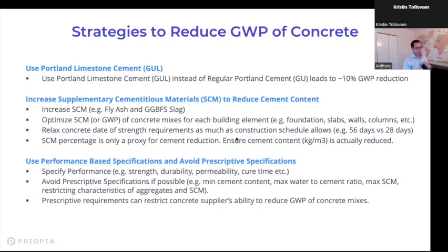And ultimately, what you're going to be requesting now is an EPD for all the different concrete mixes that are delivered to your project. That's how you're going to really know the carbon intensity of your concrete mix. The ready mix supplier may not actually tell you what their SCM percentages are, but what they're going to do is give you a GWP value for each concrete mix delivered to your project. And so you can measure from there how much reduction there is relative to a baseline.